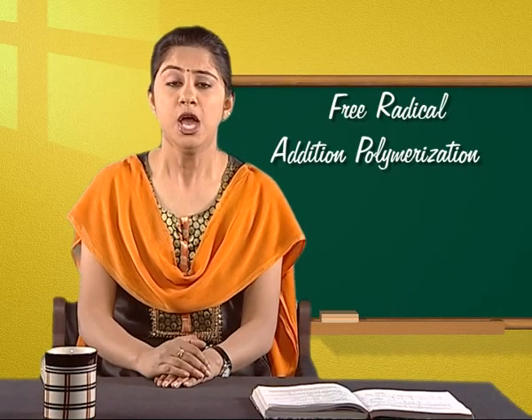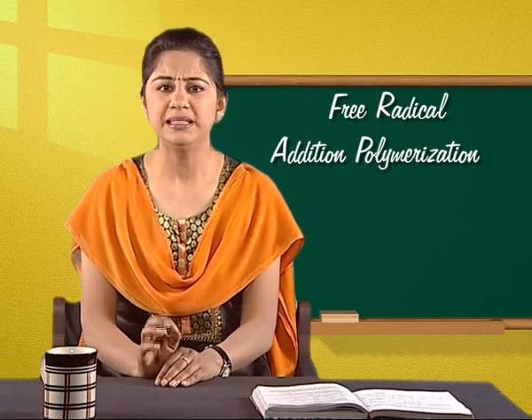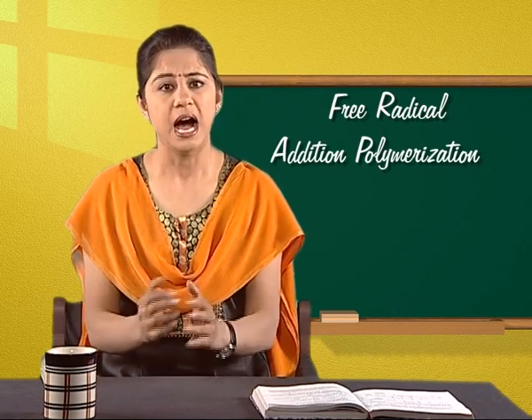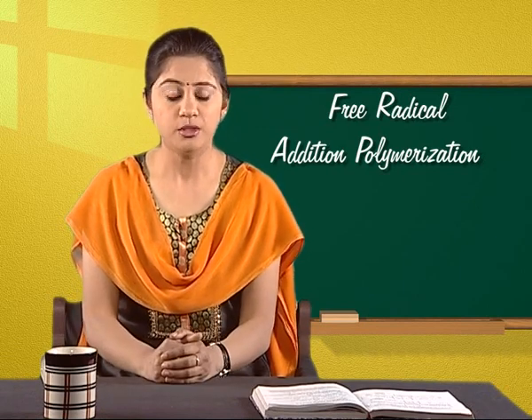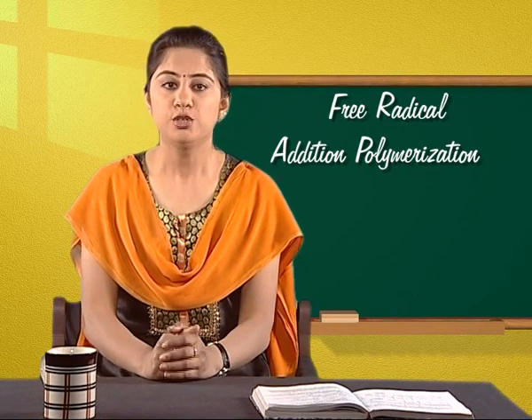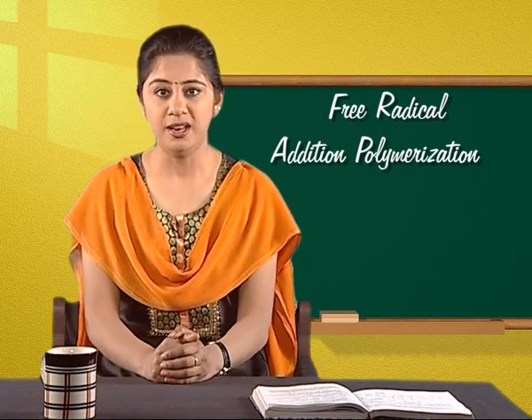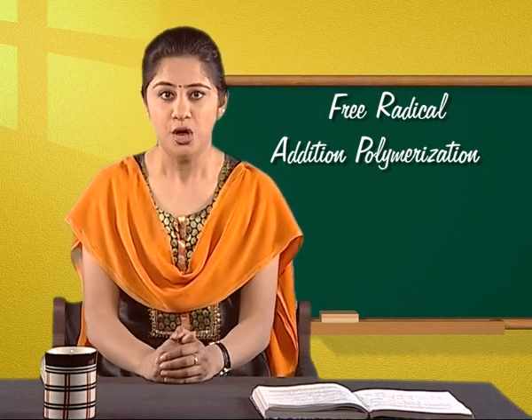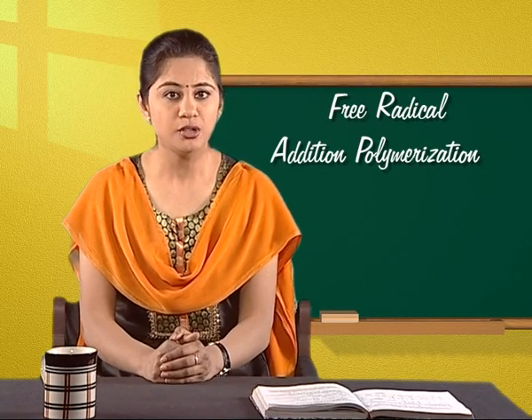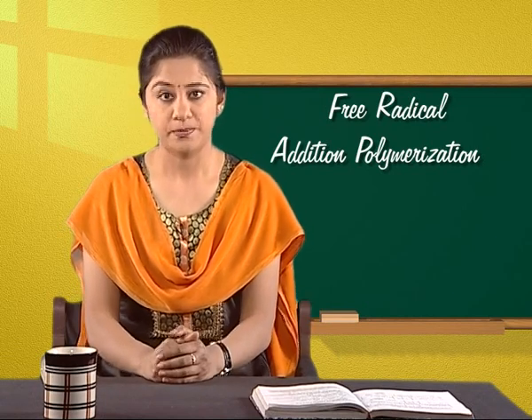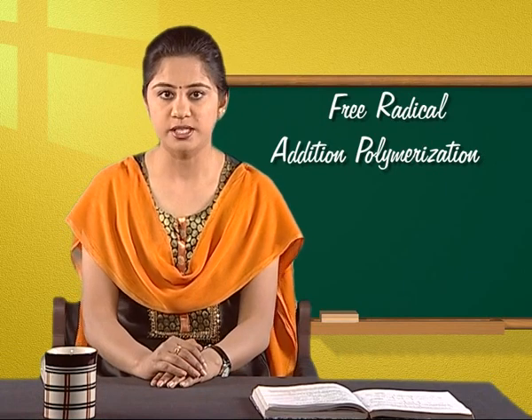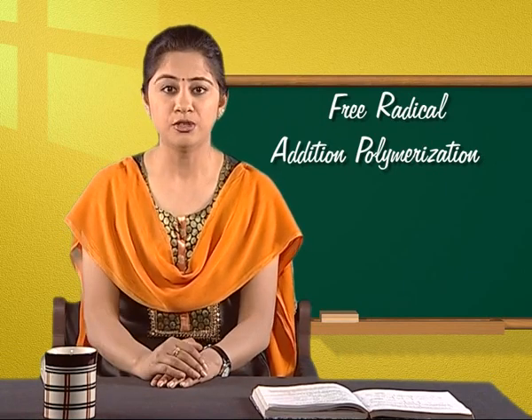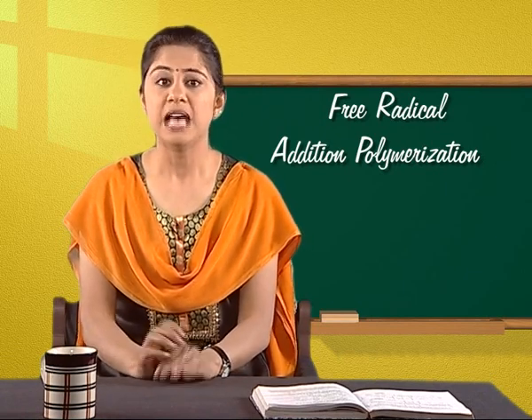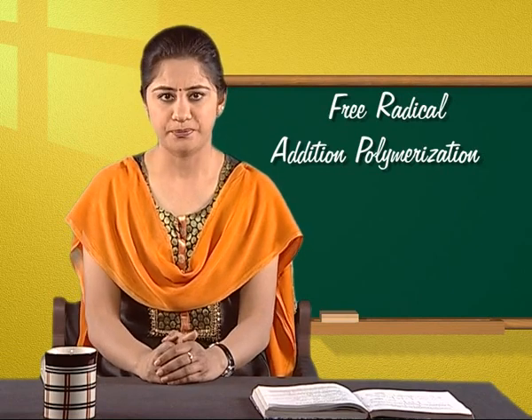For example, polymerization of ethene is carried out at a high temperature of about 350 to 570 Kelvin and at a high pressure of 1000 to 2000 atmospheres in presence of dioxygen or a small amount of benzoyl peroxide as radical initiator.